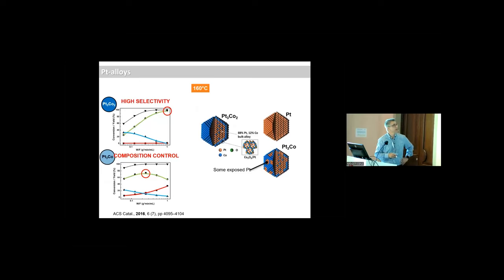Still not a perfect situation. But we can also work with the temperature, and indeed we succeeded at 160 to have high conversion, full conversion, and high selectivity, nearly 99%. So we stop completely the formation of the unwanted byproducts. While if you have less cobalt, you see you still have poor selectivity.